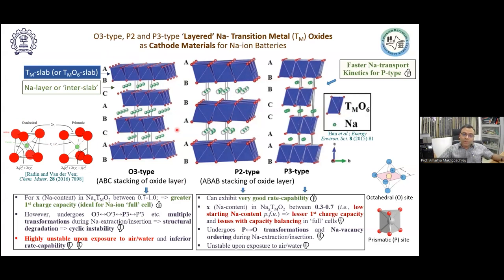type of structure. Now, O3 type of structure is exactly the same structure as lithium cobalt oxide or the lithium NMCs. It is exactly the same structure, which is a cation ordered rock salt structure. Now, the terminology O and 3 comes from the fact that O indicates octahedral coordination of sodium ions, and 3 indicates the number of stacking slabs before it starts repeating itself. So the O3 type of structure, which is basically the lithium cobalt oxide or lithium NMC structure, has sodium in